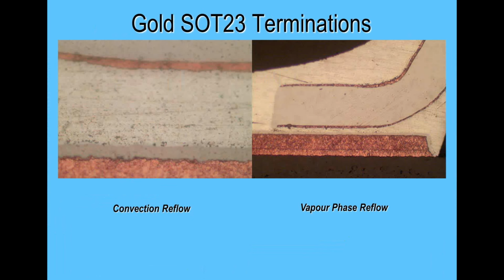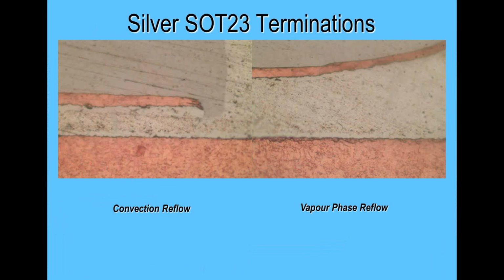If you reflow and solder for too long a period of time and dissolve all the copper from the surface of the main lead frame, then perhaps that's a reason why you've got solderability and wettability problems. So by investigating the problem, quite often you're able to find the root cause of your manufacturing defects. Now, again, just another example of some microsections, and on this occasion we're soldering to a silver finish PCB, and the intermetallic is not as obvious, and it's probably 2 or 3 microns, maybe slightly thicker, but you can see it on the bottom view between the copper.